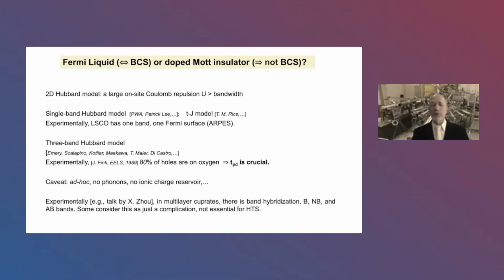Well, there is a 2D Hubbard model where we start from something that looks like tight binding, but then we add ad hoc by hand a large on-site Coulomb repulsion, U. And this has to be large enough. In mathematics, you can make it infinitely large, but the point is it needs to be larger than the bandwidth, the width of the relevant electron band, and then this becomes the dominant energy scale, and the behavior changes qualitatively. Now there are two leading contending variants: single-band and three-band models.